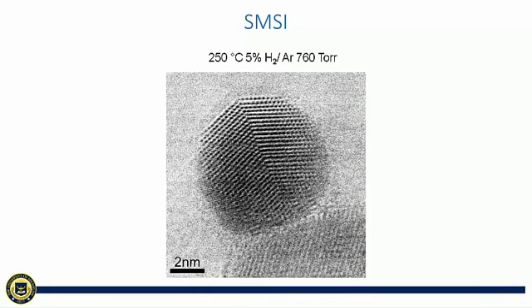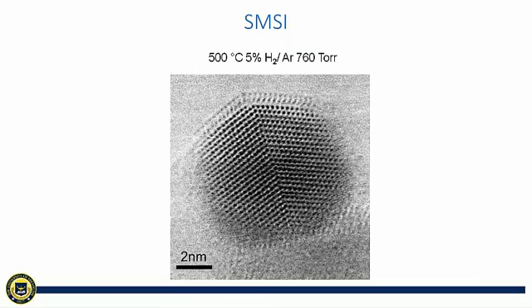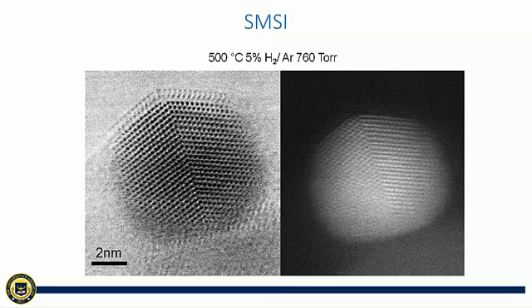This is a palladium nanoparticle supported on TiO2, and the condition that we used to acquire this image was 250 C, 5% hydrogen balanced with argon at 1 atmosphere pressure. And here we can see there is a very thin amorphous layer migrating onto the particle. And if we increase the temperature to 500 C, we can start to see the formation of a crystalline bilayer on the surface of the metal particle. If we compare with the HAADF image, which is a Z-contrast image as we have stated before, the crystalline bilayer is almost invisible in the HAADF image, indicating it has a much lower atomic number compared to the palladium nanoparticle underneath.